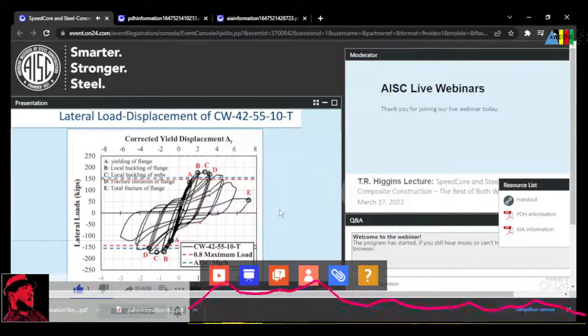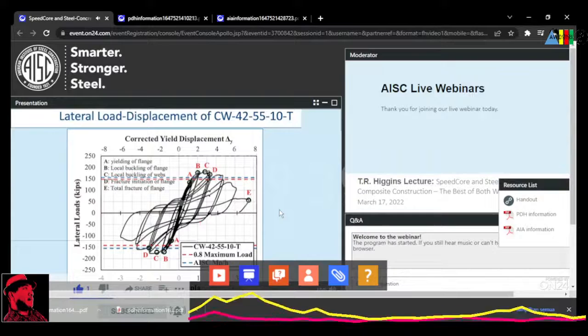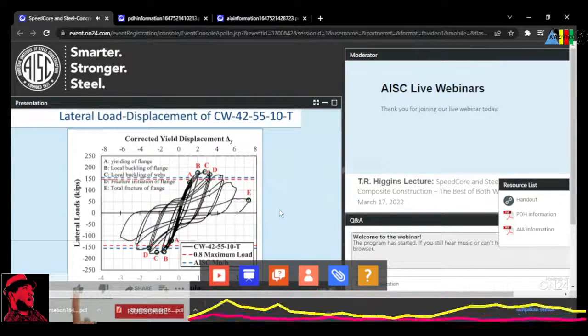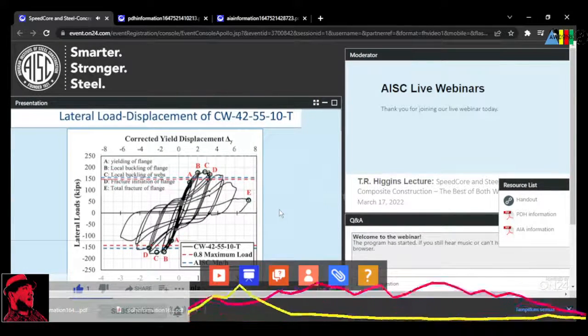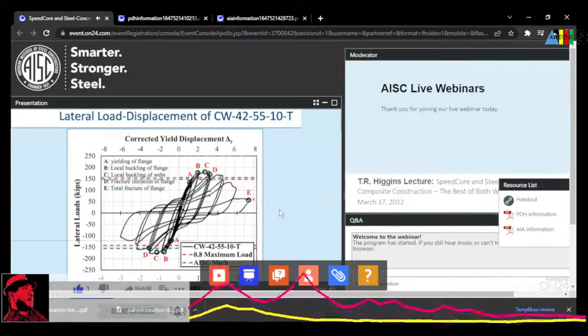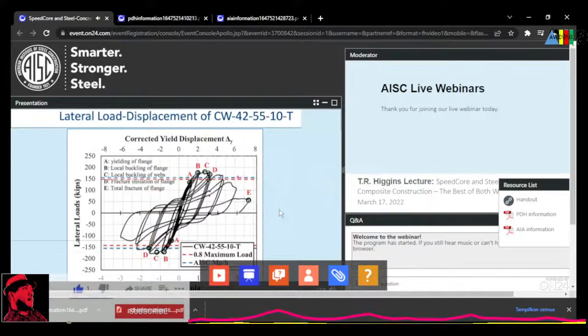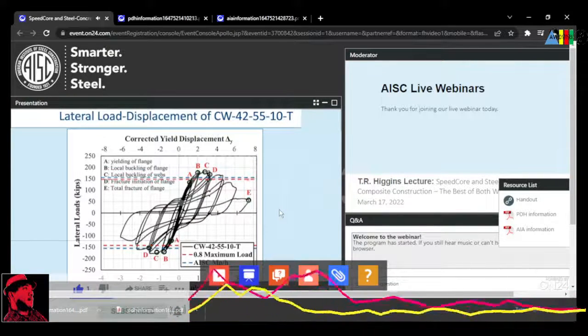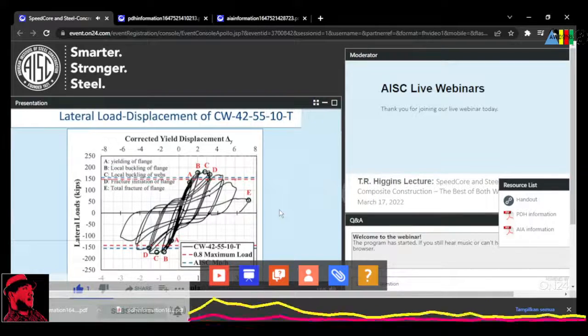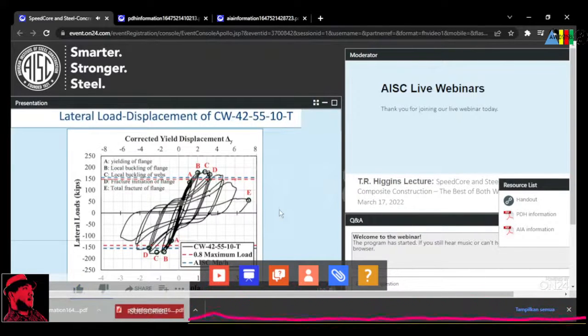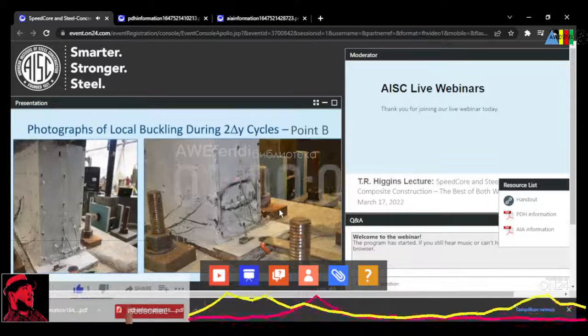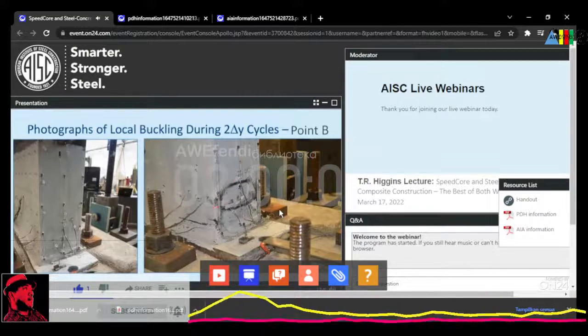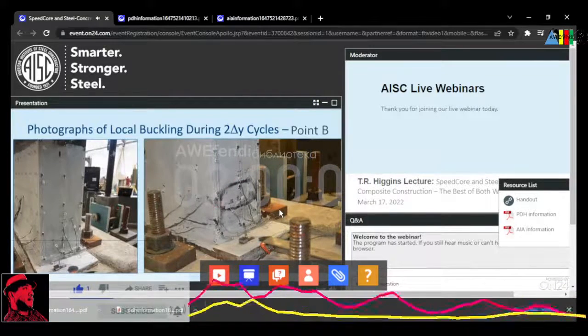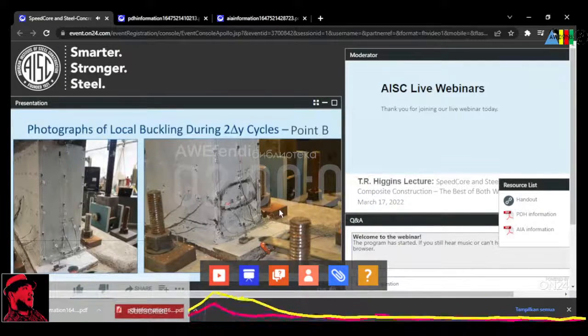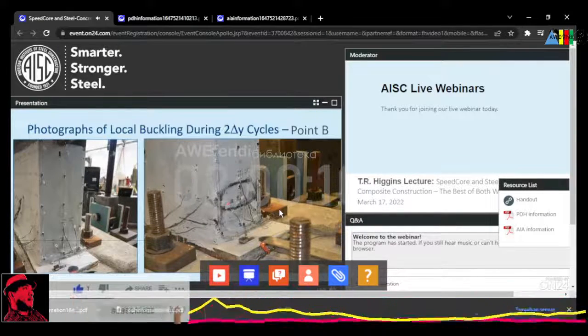As shown here, local buckling occurs after yielding but before the peak load. Fracture reduces the load capacity and eventually causes failure. The lines corresponding to the plastic moment capacity and 80% of the maximum load are also indicated here for comparison. This slide shows photographs of the specimen during yielding and local buckling initiation in the flange, which was point B during the 2 delta Y cycles.